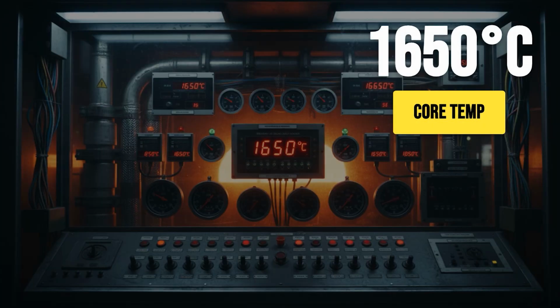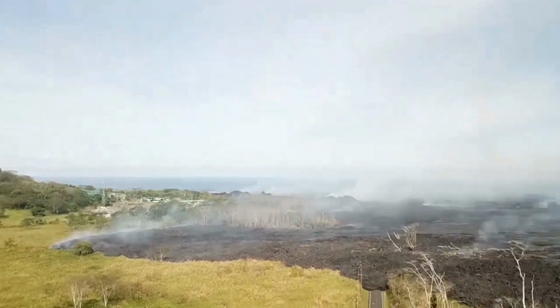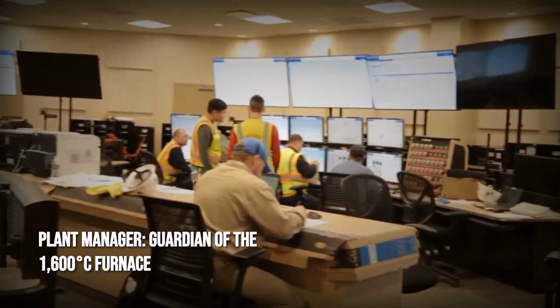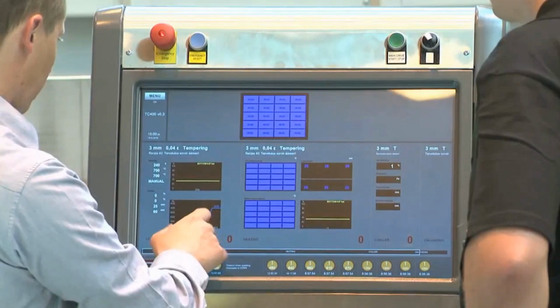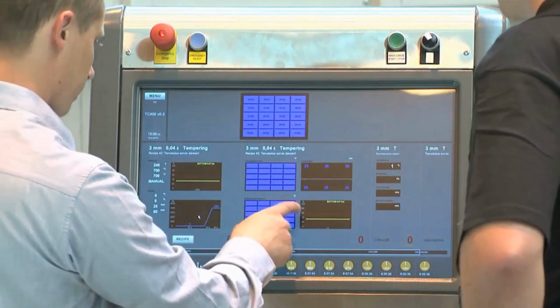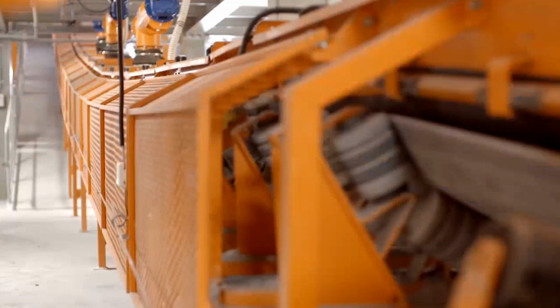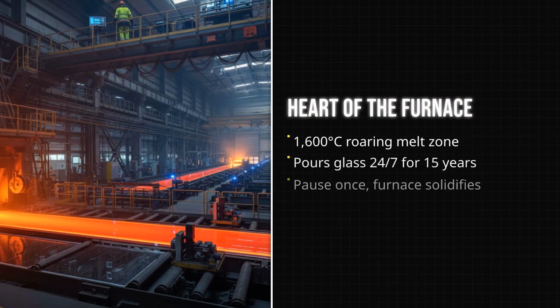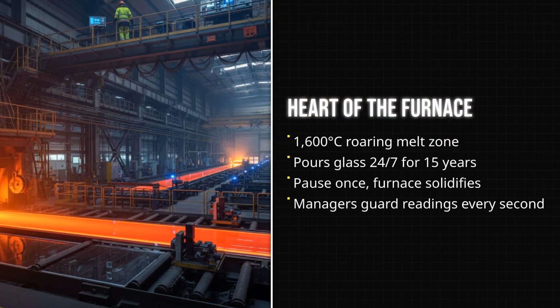Temperatures inside climb to 1,650 degrees Celsius, hotter than the surface of an erupting volcano. The plant manager, acting as both engineer and sentinel, monitors every gauge and sensor from the control room, making critical decisions that keep the furnace stable. Here, the rhythm is relentless. Raw materials and cullet are fed in at one end, while a river of molten glass flows out the other, day and night, for up to 15 years before the furnace is rebuilt.